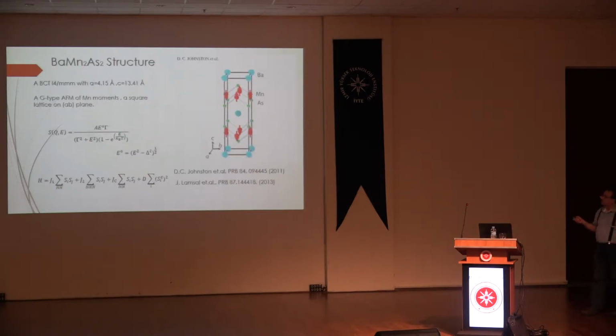So, barium manganese arsenide is this material, the single crystal. It is body-centered tetragonal, I4/mmm. As you see, the difference between a and c is huge, the lattice dimension. That means anything over this magnetic Mn plane is mostly a plane. It is not talking with the c direction. So we can easily see from just the numbers that it is a quasi two-dimensional antiferromagnetic material. It is G-type.